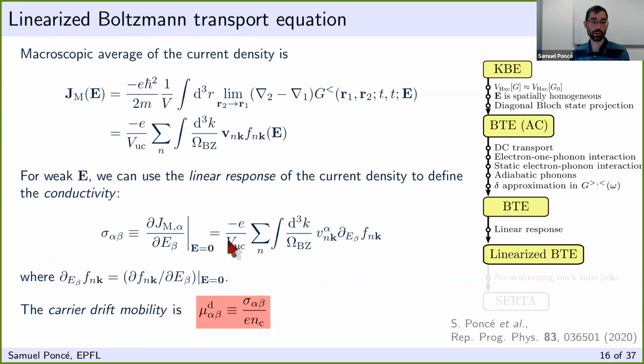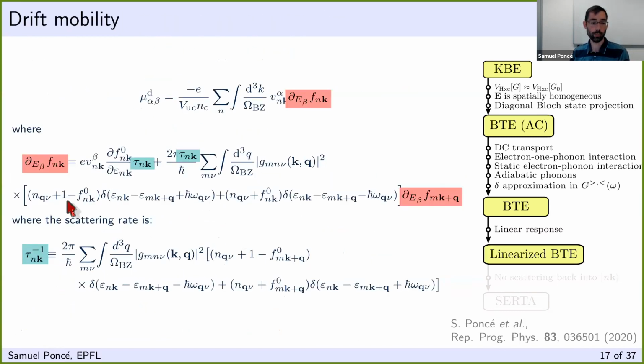But then you can also show that some of them will become F0. The F0 is the equilibrium occupation function. So this is really the Fermi-Dirac distribution function, while this N is the Bose-Einstein distribution function, again equilibrium. And then you have those energy conserving deltas. This is what we call the iterative Boltzmann transport equation, because in order to compute this term that you need here, you need to solve this equation self-consistently, because it also appears on the right-hand side at a different band and different k points.